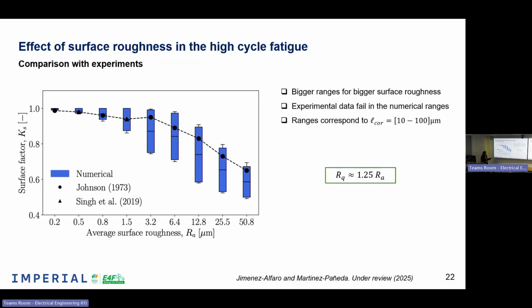So first of all, we have changed the average surface roughness, and assuming that we don't know the correlation length, that maybe is the most complex parameter that we can find, and sometimes they don't give it because they don't give the surface profile, or they just didn't think that it was interesting, then we have measured the surface factor. Since we are just considering that we know one of the two parameters that we need, we have for each value a certain range of possibilities. And then we have also highlighted here in bars the stochasticity of the distribution.